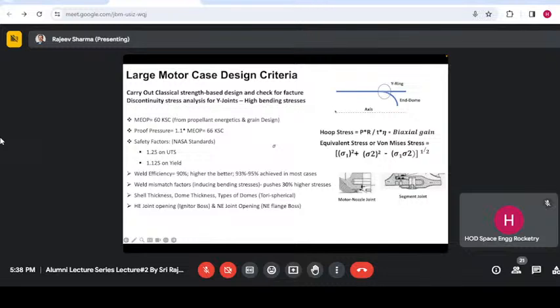And the forgings are heavy, so they will keep it down. So there are large bending stresses in the Y-ring area, in the igniter boss, and in the dome welding area at the bottom, the joints that I've shown here. This is a big forging. So you need to allow for those higher stresses.